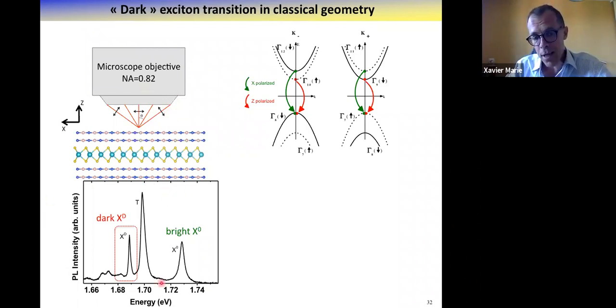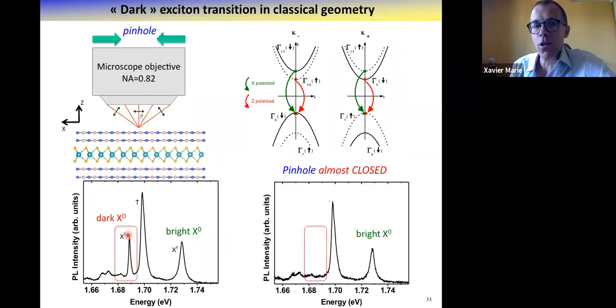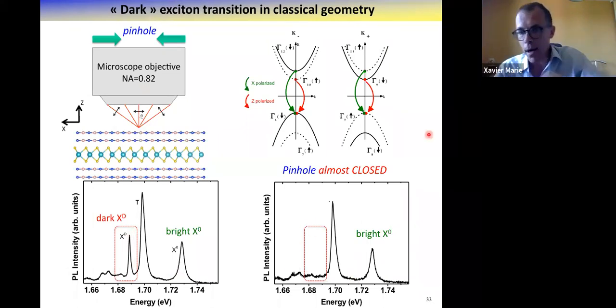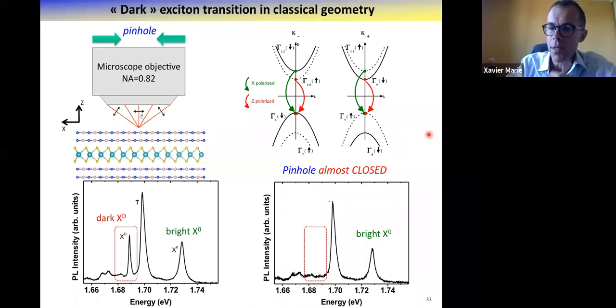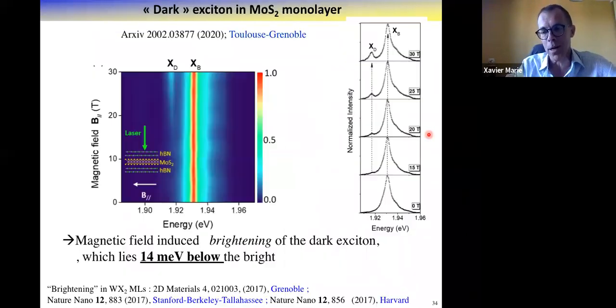So with this kind of optical configuration, indeed the dark exciton shows up at low energy, but you can prove that it is a dark exciton if you insert a pinhole to block the Z polarized component, and the dark exciton disappears. So from the symmetry of the wave function, we can get information on these optical selection rules and identify the so-called dark exciton. We call it the gray exciton because it can recombine.